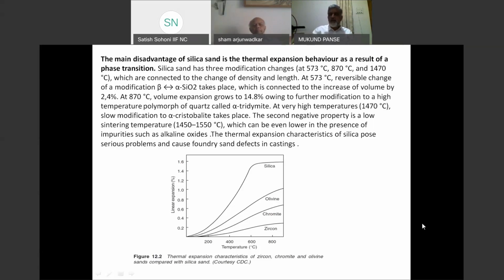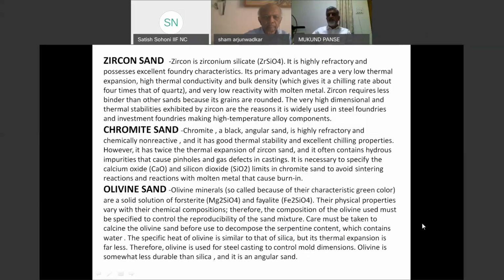These are the defects caused by expansion of the sand, and this is where silica sand is inferior to all other sands. Next sand used is zircon sand. It is zirconium silicate. It is excellent sand and meets all the requirements. It is neutral, doesn't react with most any metal. It has excellent thermal properties,